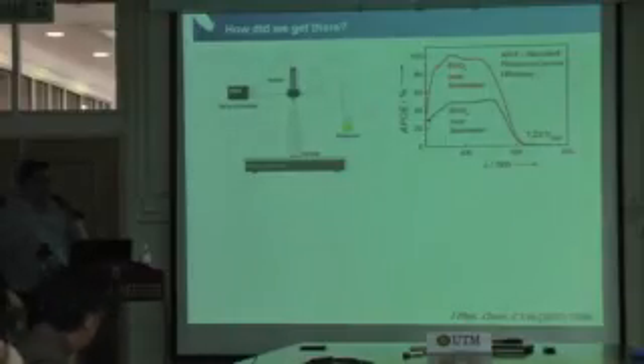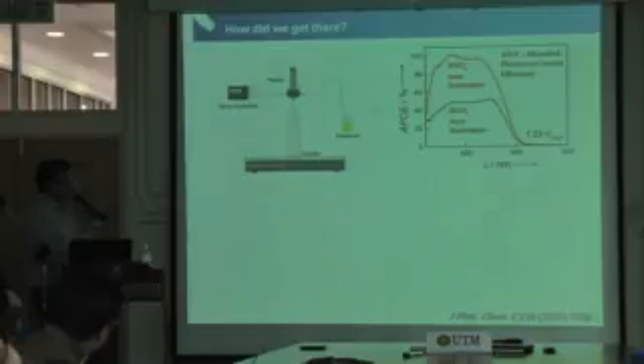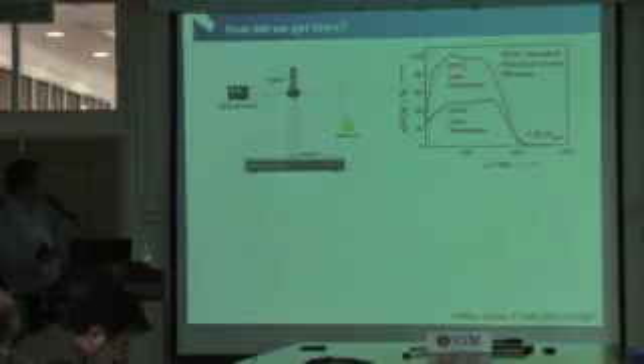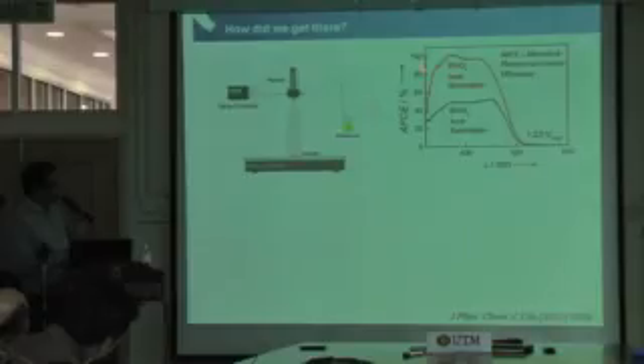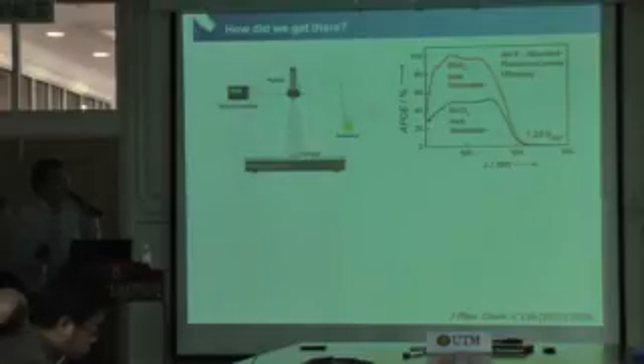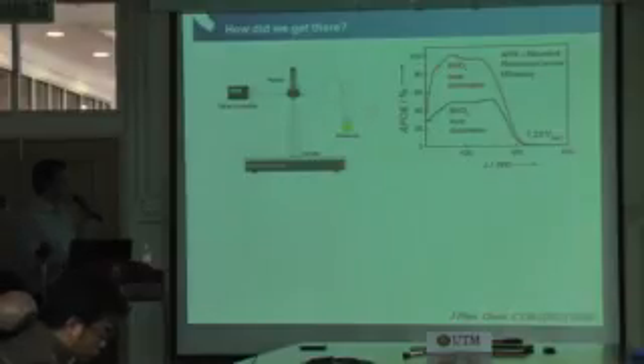So this is pretty much like airbrushing, so you can think of it. TCO, they make it this way as well. But despite the simplicity, we can actually manage to get a rather high-performing sample. So the plot on the right here is the APCE, the absorbed photon to current conversion efficiency. In the field of solar cells, this is basically internal quantum efficiency, IQE. The number of photons that you absorb compared to the number of electrons that you get at the end.